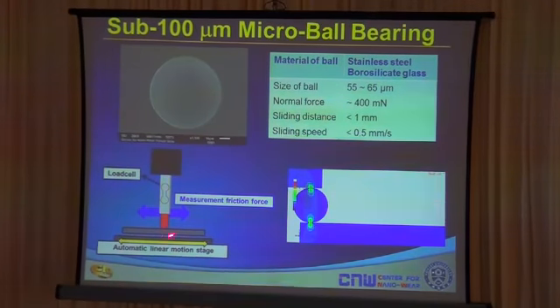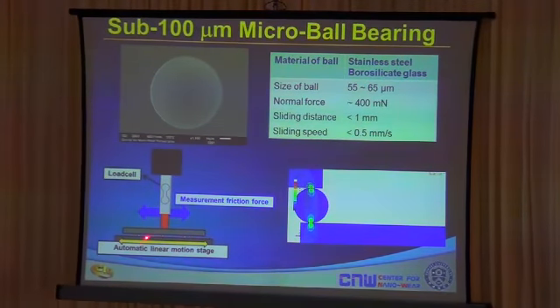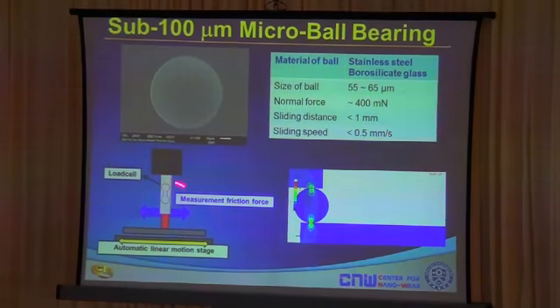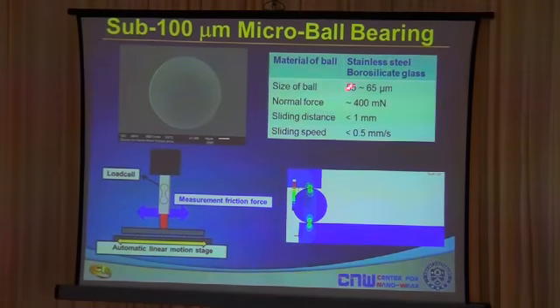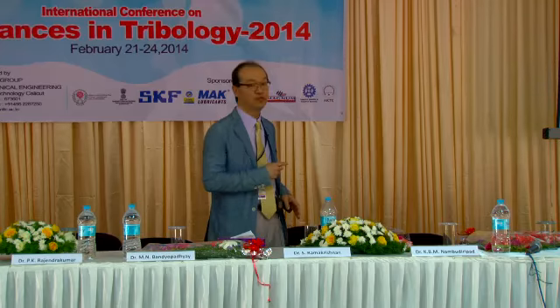And this would be the schematic of the equipment. This is the top surface, this is the bottom surface, and these are micro ball bearings placed between the two flat surfaces. And we drive the bottom stage to measure the friction force, and we monitor that by the load sensor that is attached over here. The size of the ball that we use is in diameters in the order of about 50 micrometers. That's the normal load that we use for the experiment.